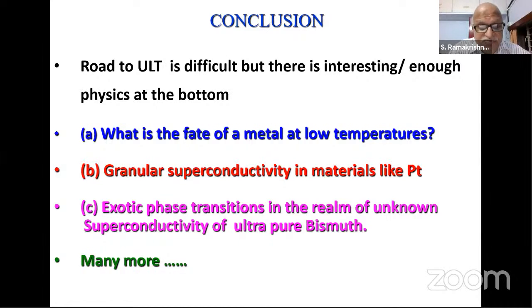And if one sees superconductivity, then one can distinguish the superconductivity we've seen in bismuth vis-a-vis the superconductivity there. Because the unusual band structure of bismuth and the temperature dependence of carrier concentration are not seen in antimony and arsenic. So we can try to distinguish something which has a similar crystal structure but different properties, and isolate whether the reason is coming from the structure or from somewhere else. That is why one would like to see superconductivity in antimony and arsenic.